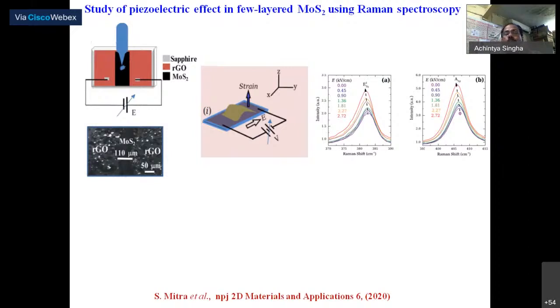The result of the Raman mode: we can see that as we increase the electric field, the mode changes from the original position to a lower frequency. So from the shift, we can measure how much strain is there. Now to confirm that this is due to the strain effect, we did the measurement by changing the polarity, that is, we reversed the field direction, and we can see that. Go next.